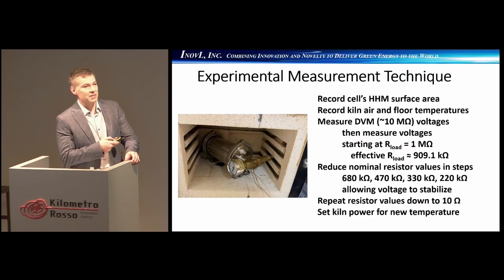And hopefully when you're assembling the plane parallel one, you happen to capture the surface area that you put on for your active material. We record temperature as the floor temperature. We have a thermocouple on the floor of the kiln and also an air temperature. And we take an average of that. We don't currently have a thermocouple inside the pressure vessel. And then you measure the voltage that's coming out. And while we're waiting for it to recover, we monitor the open circuit. And then once it finally appears to have stabilized, the kiln has stabilized, you do your initial load test.